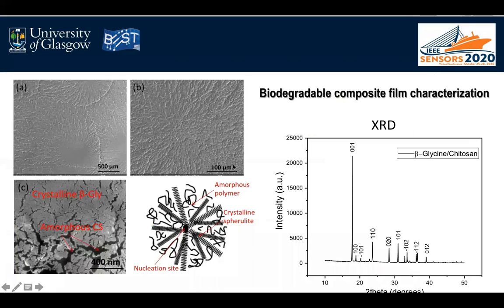And here is the SEM image of the film with the 0.8 to 1 ratio of glycine to chitosan. It shows how well the glycine crystals are embedded in the amorphous chitosan matrix, and each of these crystals is like a spherulite with a nucleation point in the center, and then the fibrils of the spherulite radiate out from this center. And you can see they are embedded in the amorphous chitosan matrix.